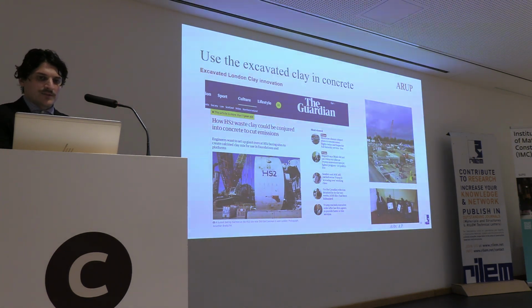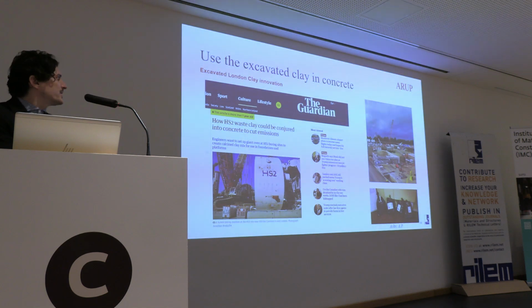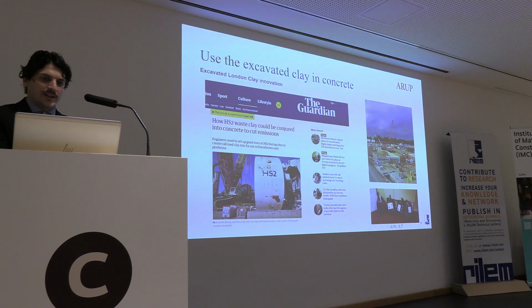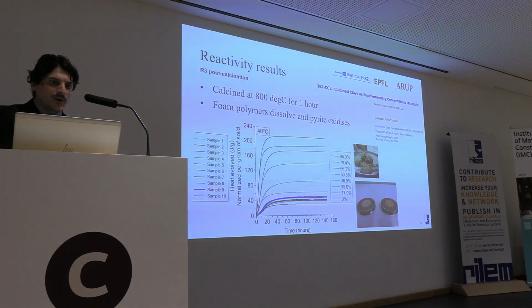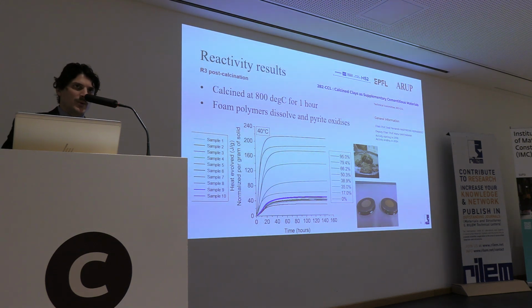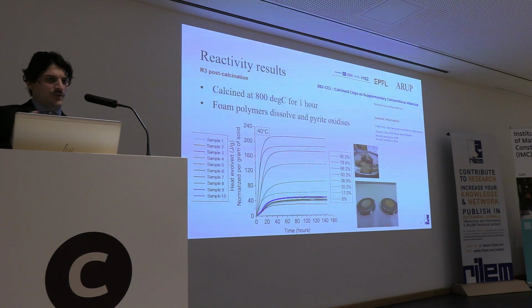And here are some examples of the initial studies that we carried out in 2018, where we initiated the first part of that innovation. Here's a collection point of clay, and here are some samples collected by colleagues from the contractor, SCS JV. At that point, we found out from initial studies that the clay was quite low grade, with low kaolinite content, around 12 to 25%. So there was a concern about the suitability of the clay for producing calcined clay for use in concrete.